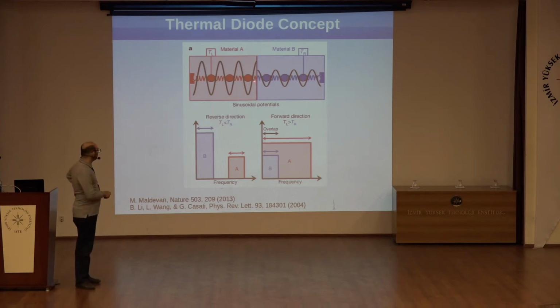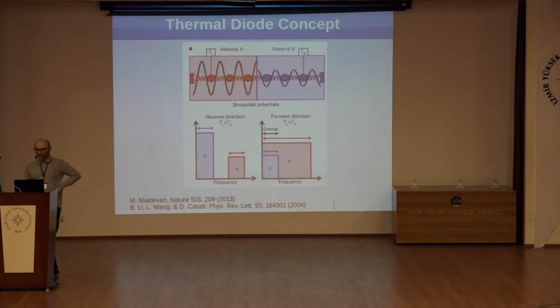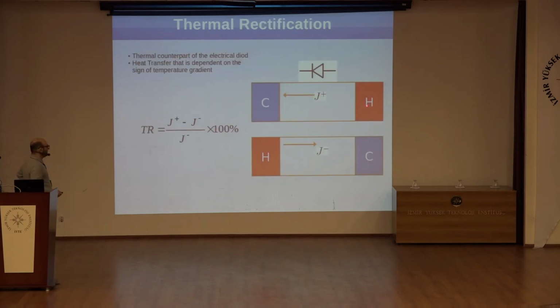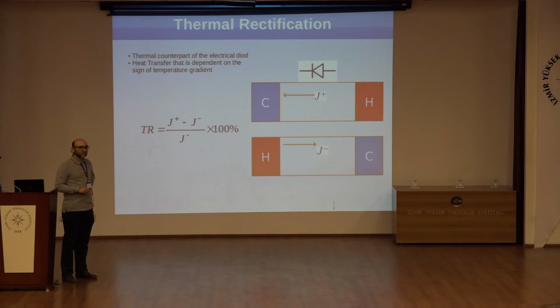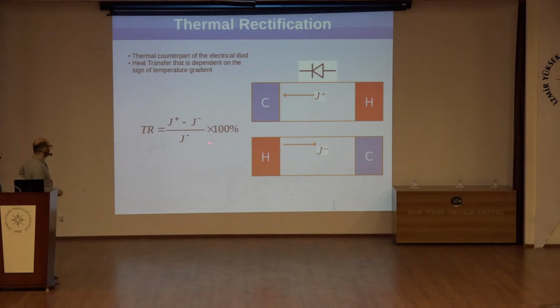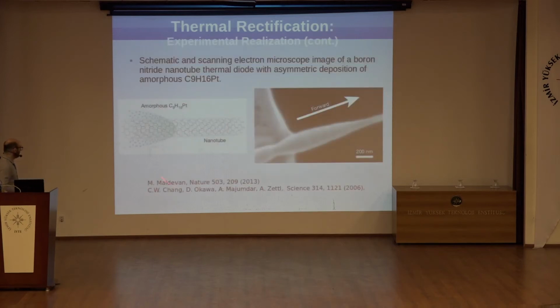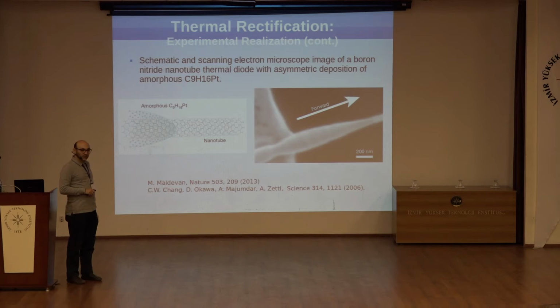It means that we have a lot of scattering at the boundary to carry heat from one side to the other side. It means that when we have a plus or minus heat current, we will have some sort of rectification, similar to what we have in electrical conductivity, that we parameterize by the TR sign. After a few years, it was experimentally observed by one group, Majumdar group, I think, that it is possible to get thermal rectification in mass-graded boron nitride nanotubes.